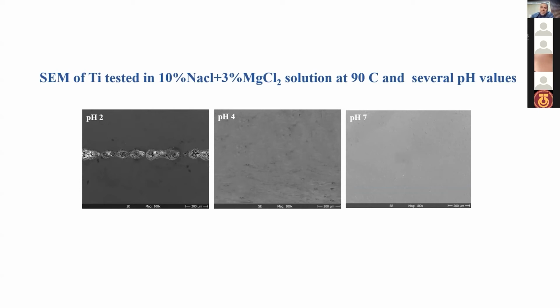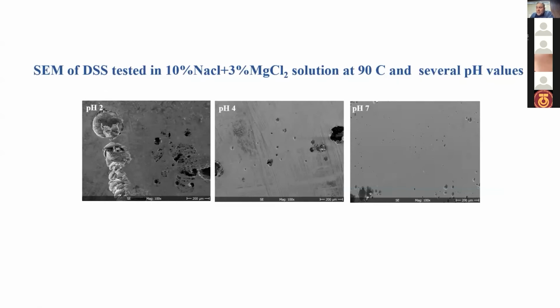Now we can explain these results. The addition of magnesium chloride played an important factor in increasing the corrosion rates of the two alloys, and this is consistent with what was stated in previous studies, where it is found that the increase of the corrosion rate is due to the magnesium chloride solution having a higher viscosity and stronger hydrophilicity than the sodium chloride solution, which makes the magnesium chloride molecules stick and crystallize on the surface and react with the metal quickly.